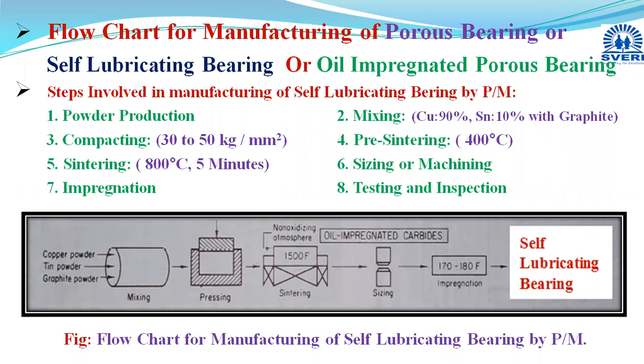Means the powder is very loosely attached. It will get separated from that component. And suppose you have exceeded the pressure values, you are using more pressure, then what will happen? Here, this punch wall or this die cavity wall may get damaged. Hence, you have to use the pressure values within this range only, 30 to 50 kg per mm square, for